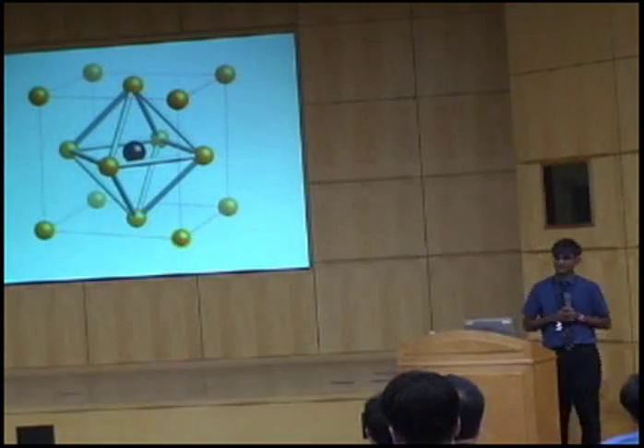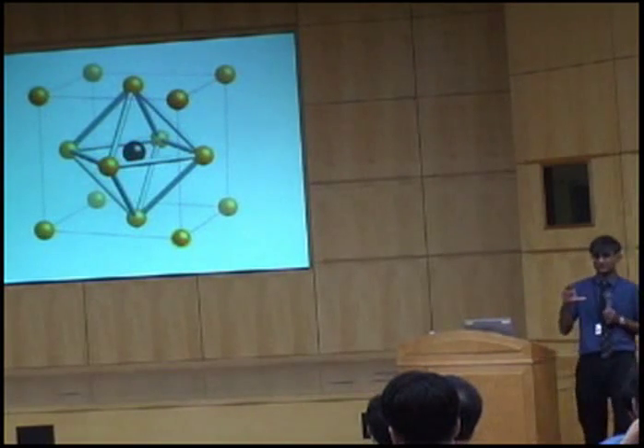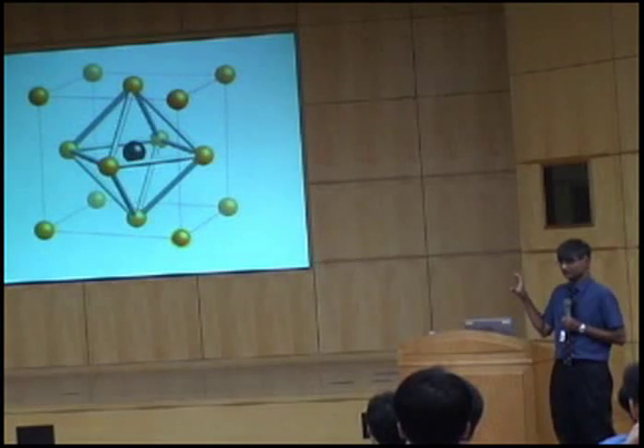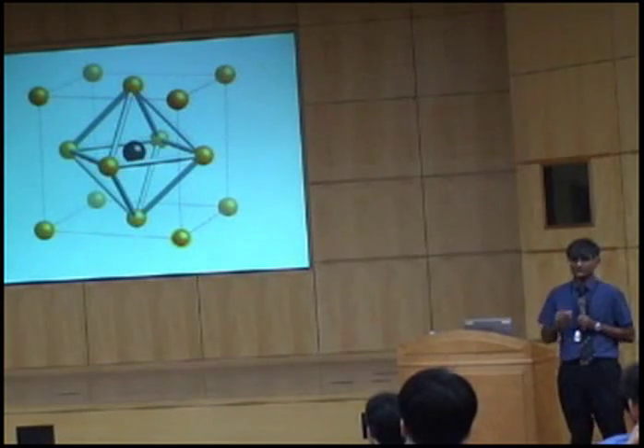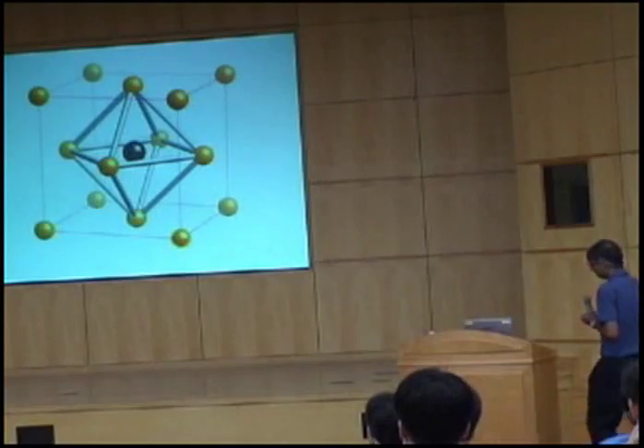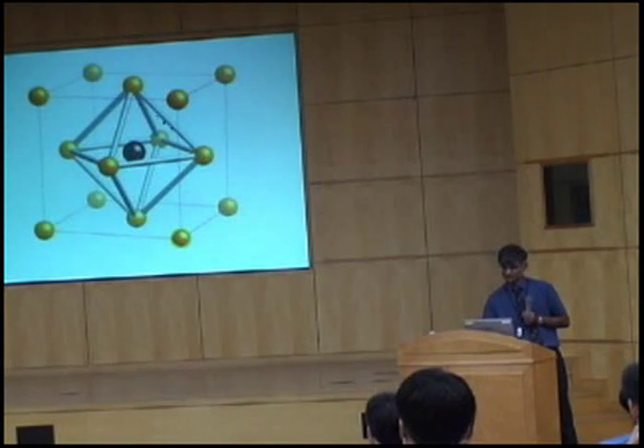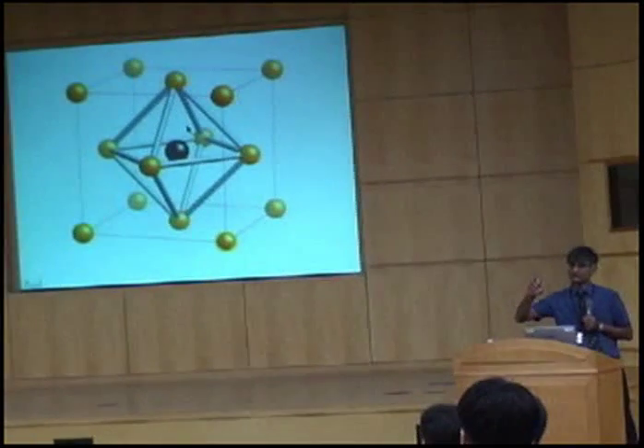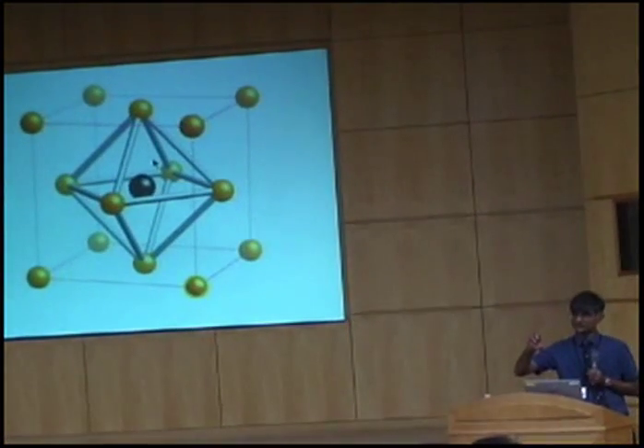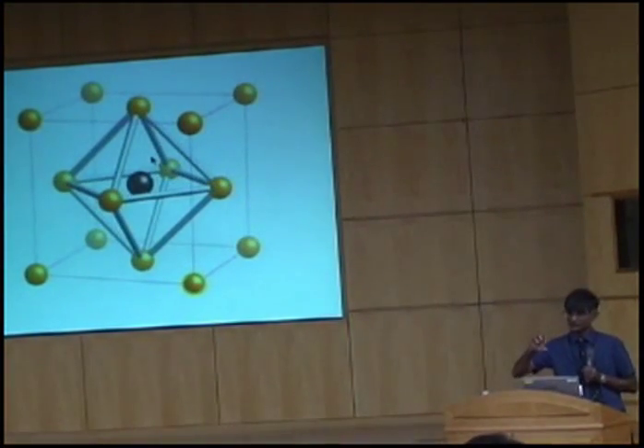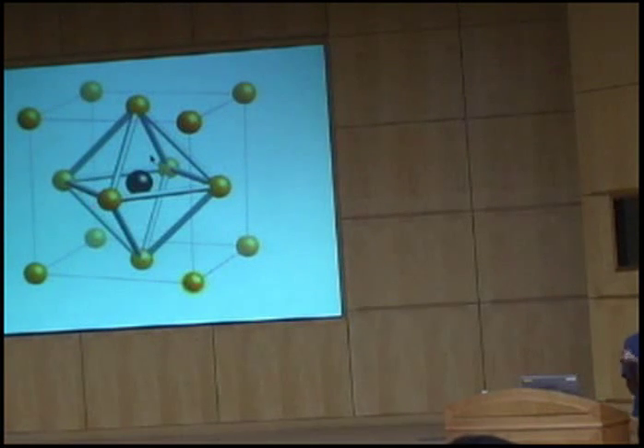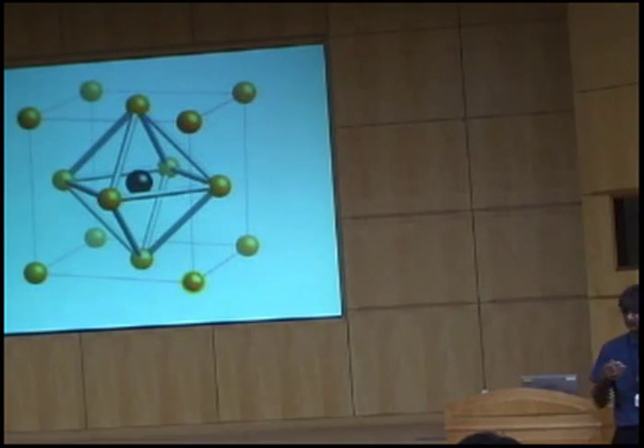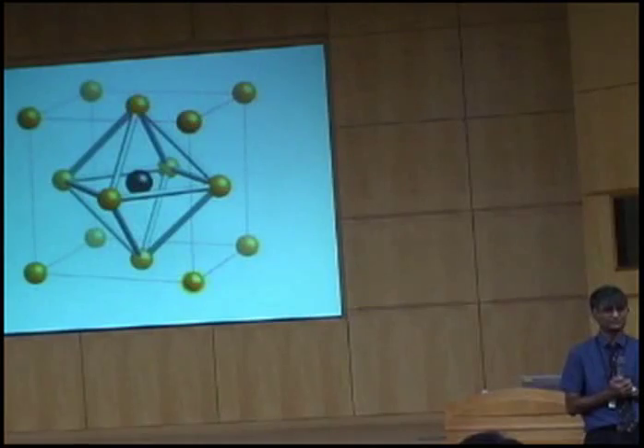So this is the carbon atom inside the lattice of austenite, and you can see that it's a regular octahedron. By regular octahedron I mean that all of these edges are of equal length. So the expansion caused by carbon is isotropic. Yeah? So carbon in austenite behaves like interstitial solid solution strengthening. It's not a very large effect.